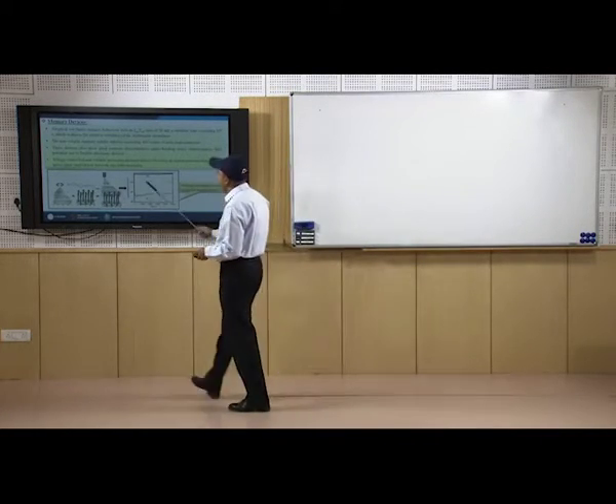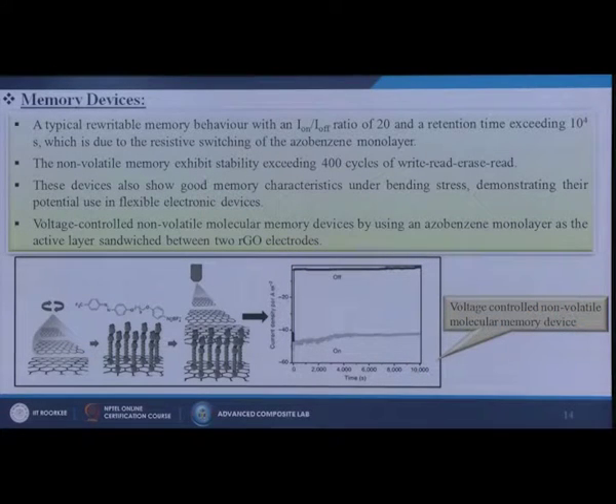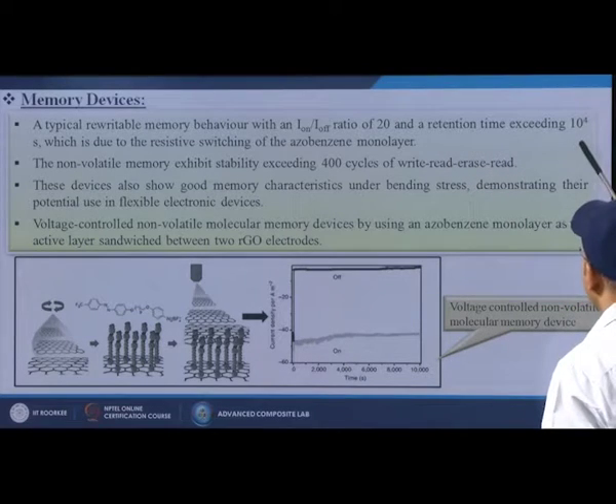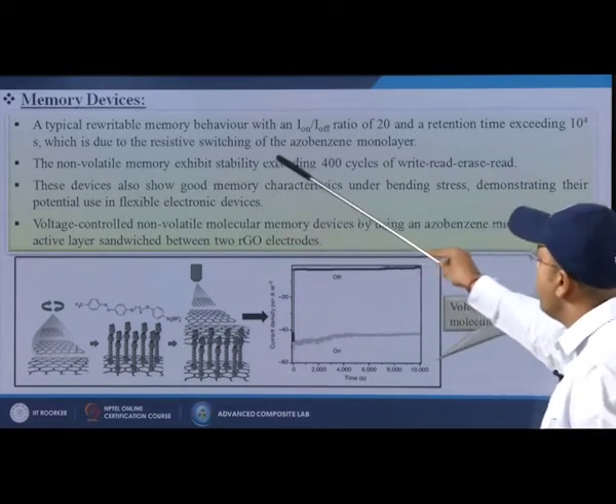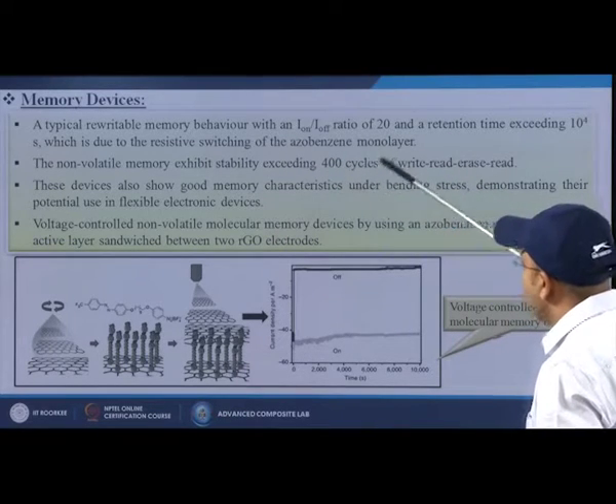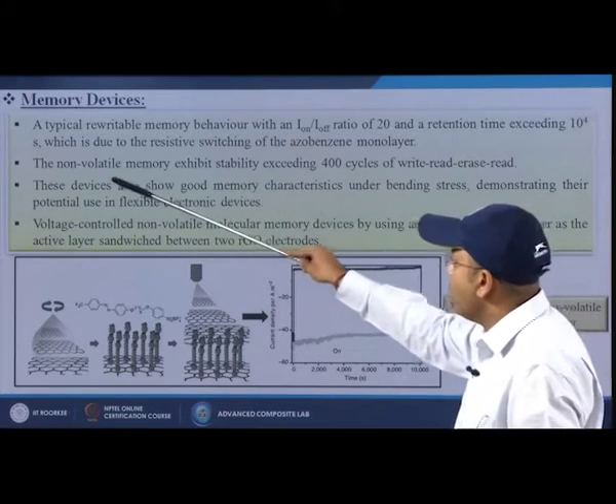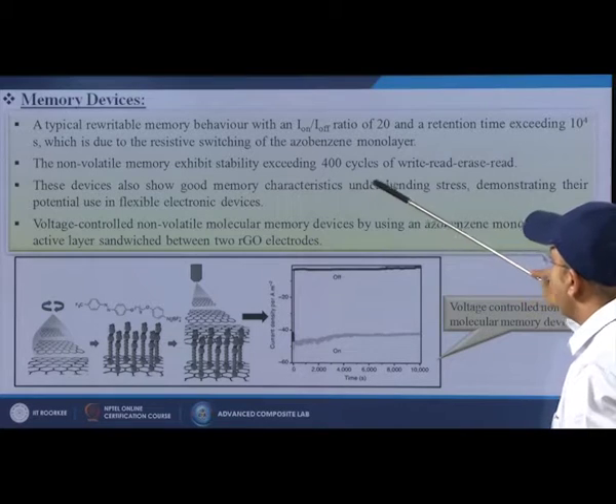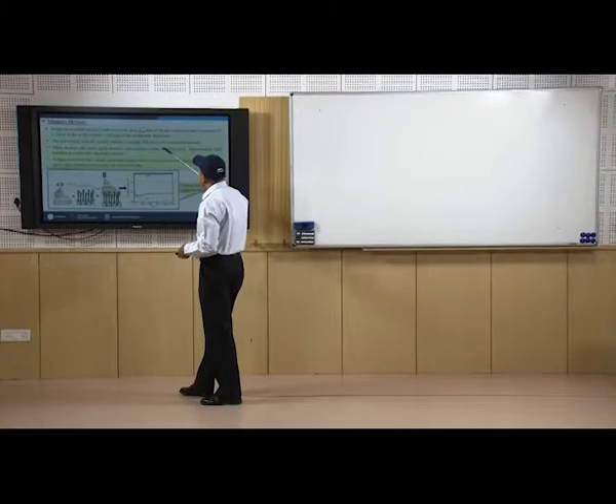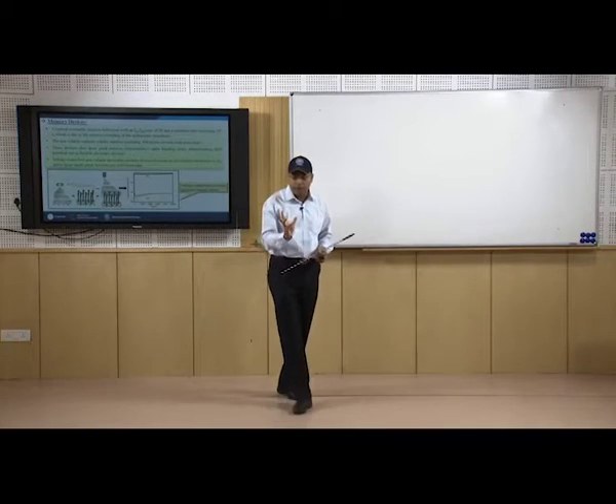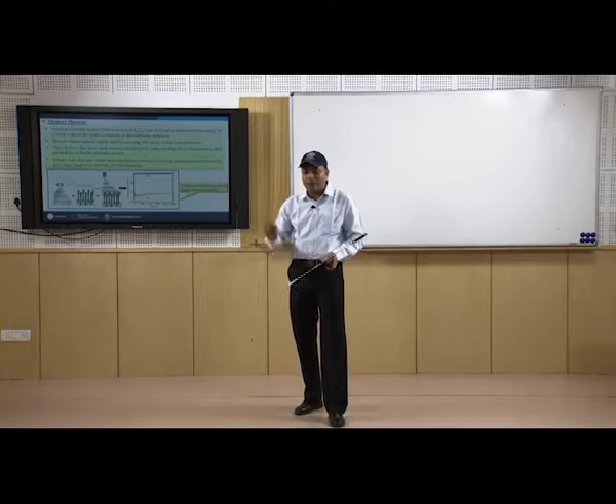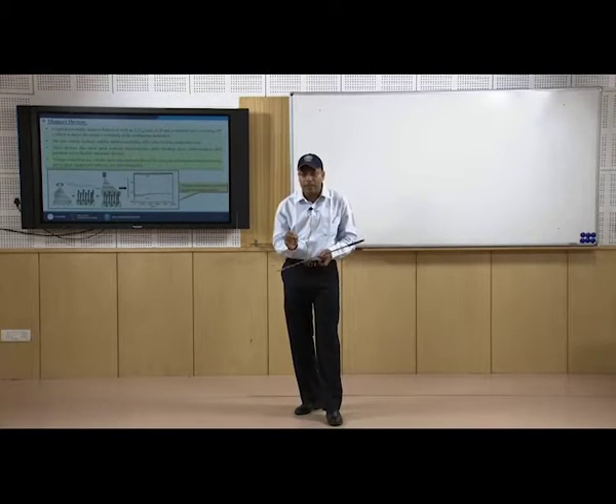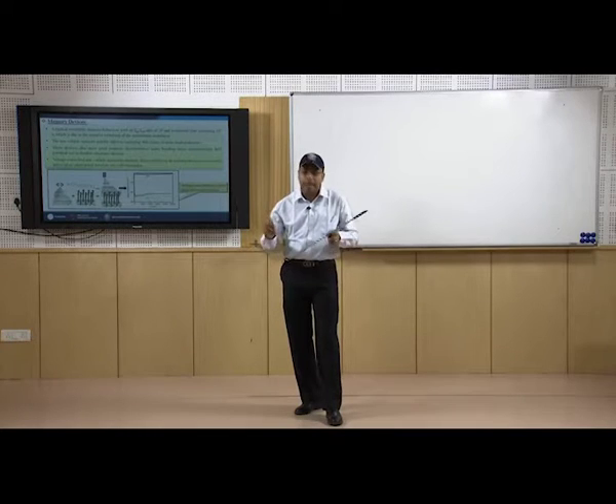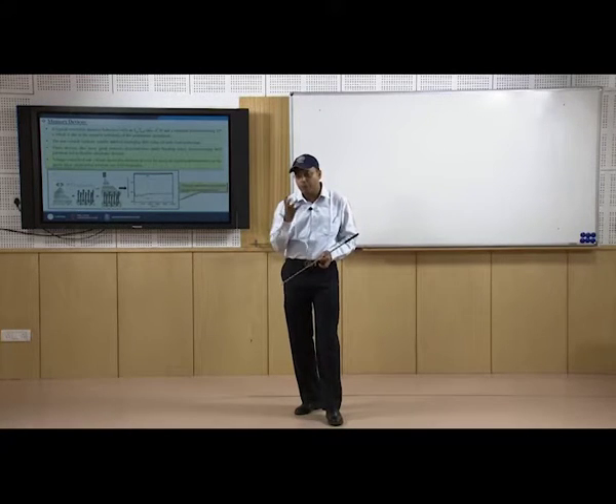Not only that, it should be lightweight, less expensive, and easily made. So, here is a typical rewritable memory behavior with an I on to I off ratio of 20 and a retention time exceeding 10 to the power 4 seconds, which is due to the resistive switching of the azobenzene monolayer. So, here we are functionalizing this kind of material with azobenzene. The non-volatile memory exhibits stability exceeding 400 cycles of write, read, erase, read. Previously, with a CD, we could only write materials inside it, but we couldn't delete them. But nowadays, with the storage systems we use, we can simply erase and delete materials, then again store new materials. So, read, write, or erase, every facility is possible for these systems.